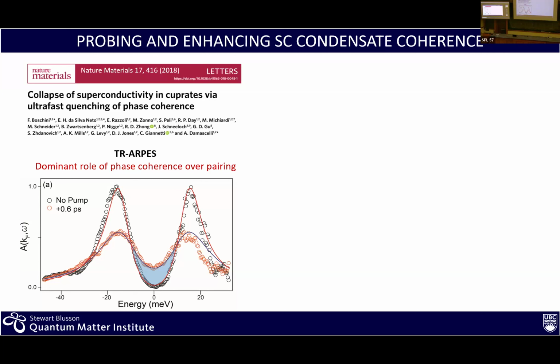If you want to take it to the next step, this is what I will talk about tomorrow. You can use the same technique. This is actually work done by Fabio Boschini, now a faculty member in Montreal, and Eduardo, when they both were postdocs in my group. And what you can see here is basically the superconducting gap of the cuprate. The sharp peaks are before the pump comes in, and then the pump comes in, and what you see is a redistribution of spectral weight here.